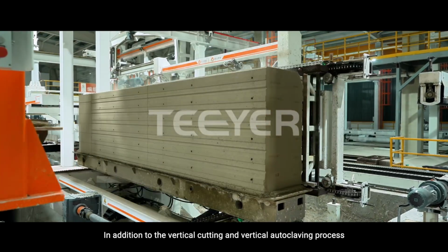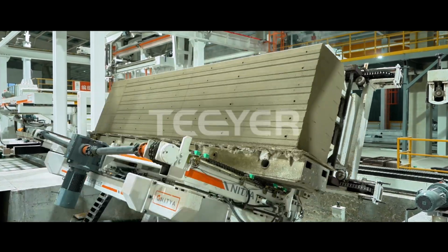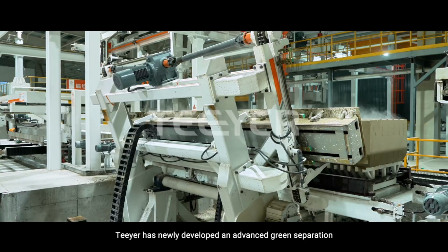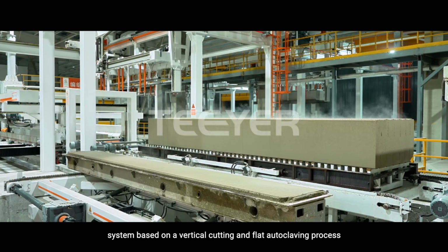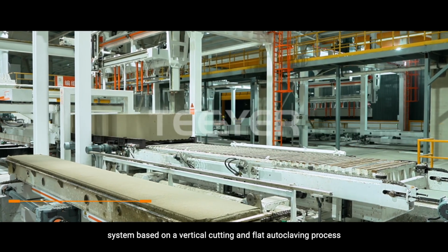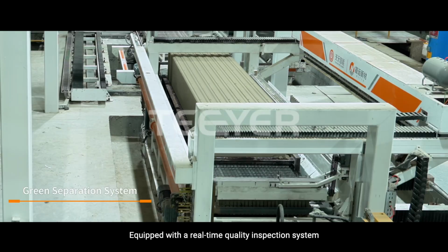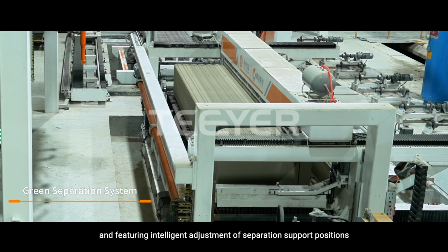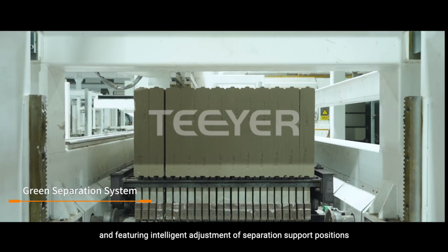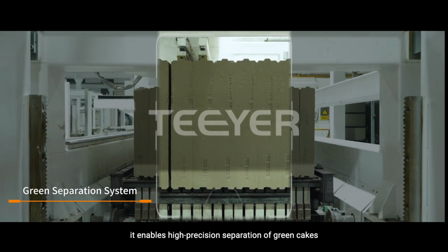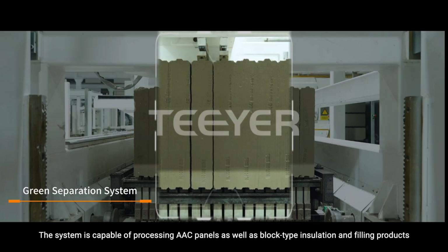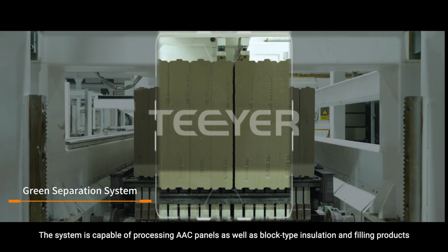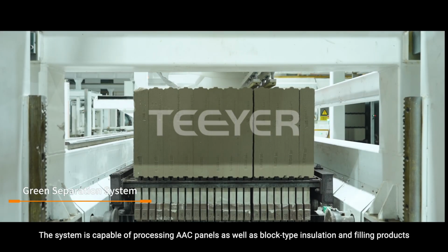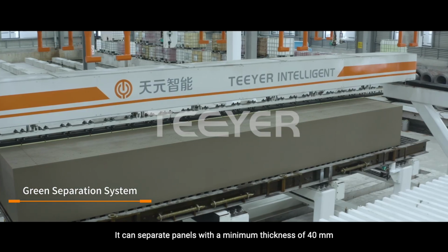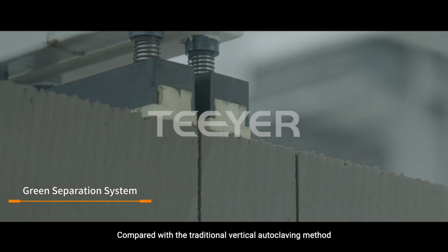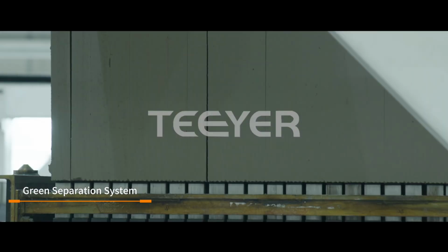In addition to the vertical cutting and vertical autoclaving process, Teeyer has newly developed an advanced green separation system based on a vertical cutting and flat autoclaving process, equipped with a real-time quality inspection system, and featuring intelligent adjustment of separation support positions. It enables high-precision separation of green cakes. The system is capable of processing AAC panels as well as block-type insulation and filling products. It can separate panels with a minimum thickness of 40 mm compared with the traditional vertical autoclaving method.